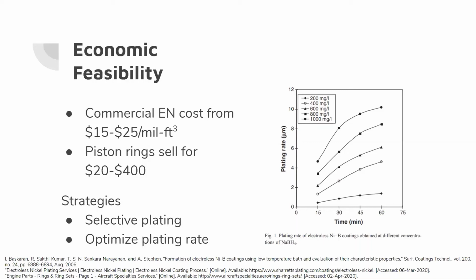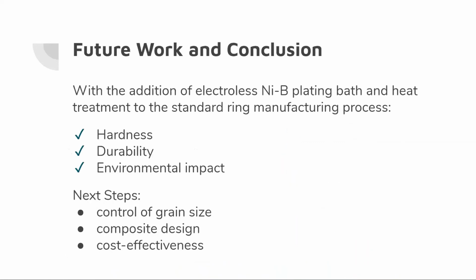If we move on to the next slide, we can see that by adding the plating bath treatment and also the heat treatment to the standard ring manufacturing process, we're able to increase the hardness, increase the durability, and also reduce the environmental impact of this process as compared to the current chromium plating.